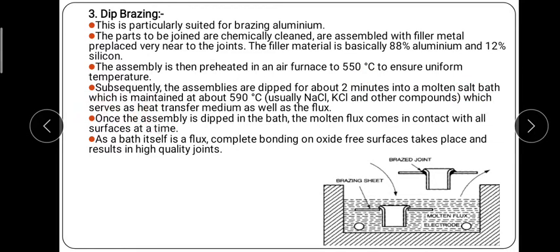This molten salt bath serves as a heat transfer medium as well as the flux. So this heat transfer medium melts the filler metal and fills the joints between the two metal surfaces. Once the assembly is dipped in the bath, the molten flux comes in contact with all the surfaces at a time. As this bath itself is a flux, complete bonding and an oxide-free surface result, giving high-quality joints. The molten salt bath acts as a flux and does not allow oxidation. So at the end, we get a brazed joint.